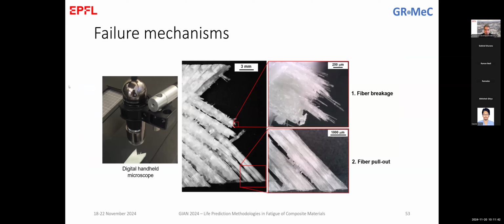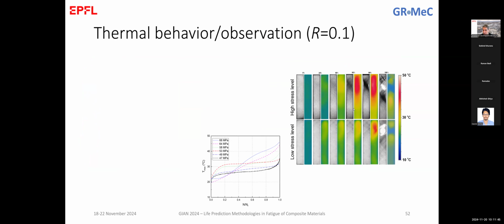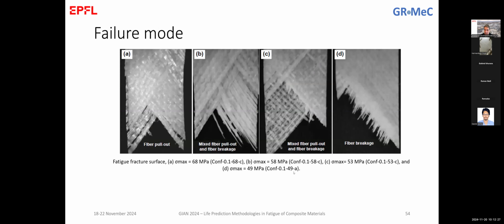If I go back to these observations, this photo shows a comparison between the high stress level and the low stress level, and we can see these effects. In high stress levels, we have localized damage that led exactly to this fiber pull-out. In lower stress levels, we have distributed damage. You don't see any significant damage concentration; the damage is spread all around the specimen, and this is the reason that damage is accumulated there as matrix failures and causes this failure mode at the end.